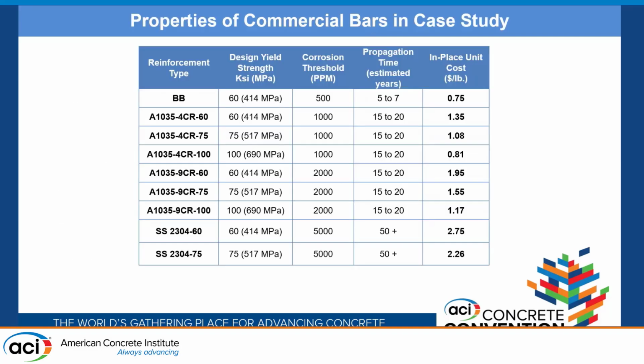So anyways, the first thing we look at is the black bar, and we're using a Grade 60, which is the common one, with a threshold value of 500 parts per million chloride total in the concrete by mass of the concrete, and the propagation typically 5 to 7 years after corrosion starts. That also came from a SHRP study that I worked on with Mike and Richard Wires, where they looked at bridges and it took about 5 to 7 years after corrosion started to start seeing cracking and spalling on the surface. It might vary from location to location, but that's a good number unless you have local data to say otherwise. And at today's prices, it's roughly 75 cents a pound for buying that bar. It might be more or less depending where you're at, but that's roughly the price.